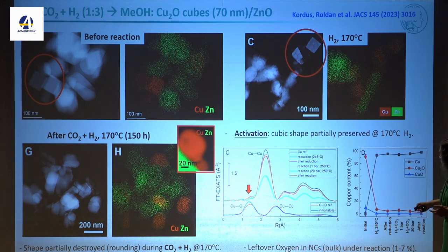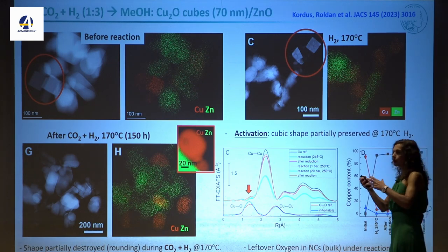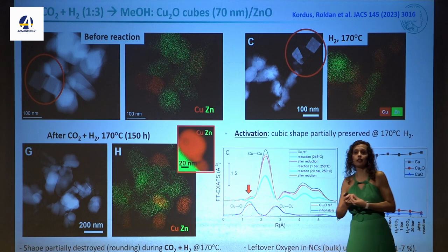We have, again, X-ray absorption spectroscopy under reaction conditions, and 1 bar and 20 bar. And you can see that this is the copper-copper signal, and this is the initial nanoparticles have metallic copper and the copper-oxygen bonds. Then we start going to the reaction conditions, about 250 Celsius, 20 bar, and this peak starts increasing, so you see more metallic copper. But this doesn't get completely reduced, and this is the copper-oxygen bond. So when you start with this copper oxide precatalyst, some oxygen is retained in the material.